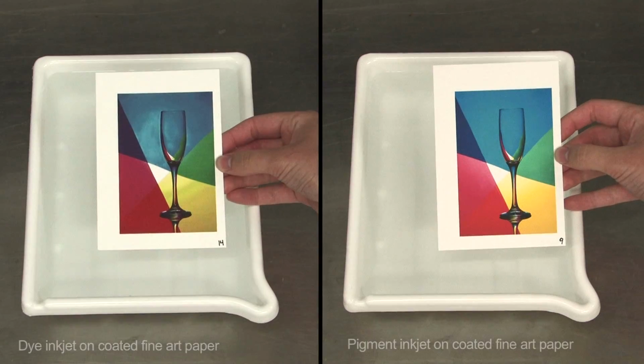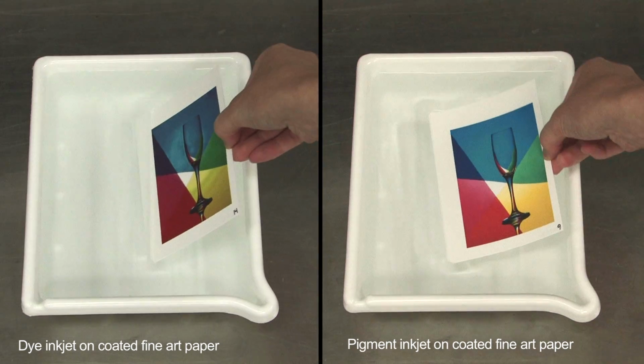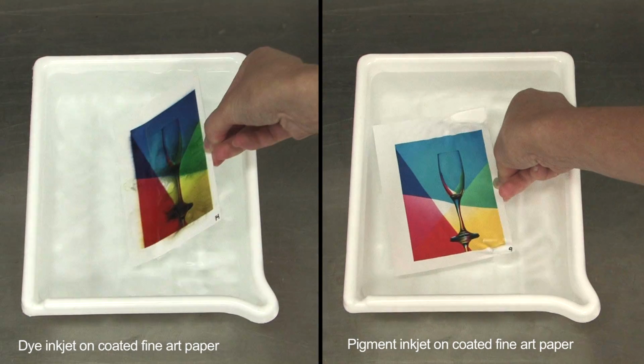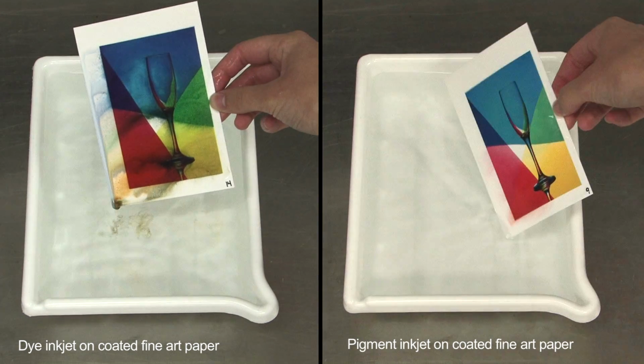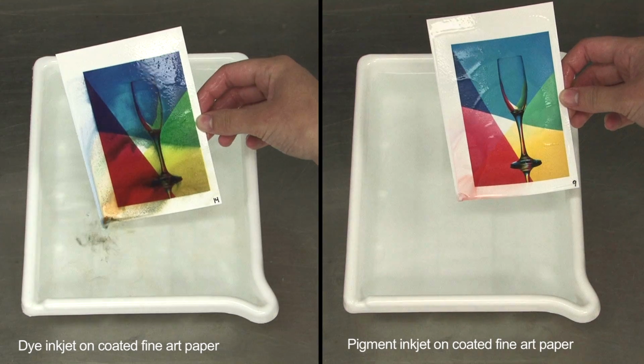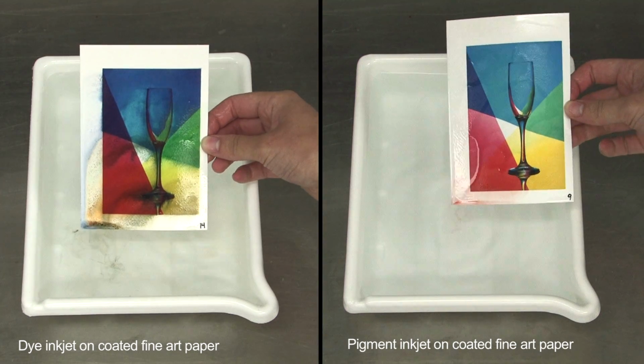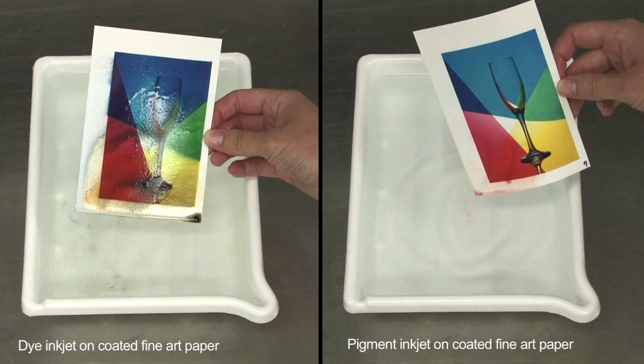These samples were both printed on coated fine art papers. The sample on the left was printed using an iris dye printer, while the sample on the right was printed using a modern pigment printer. Again, the dye print bleeds significantly despite the coating.